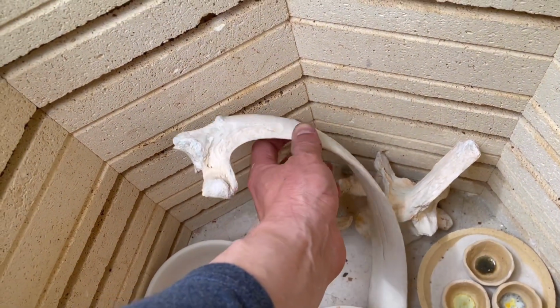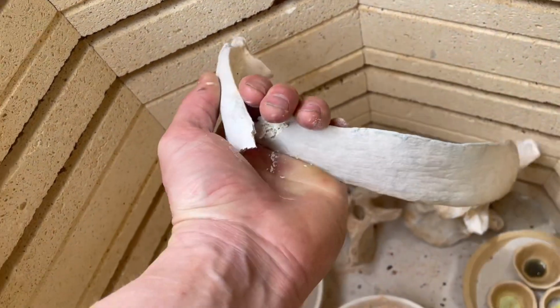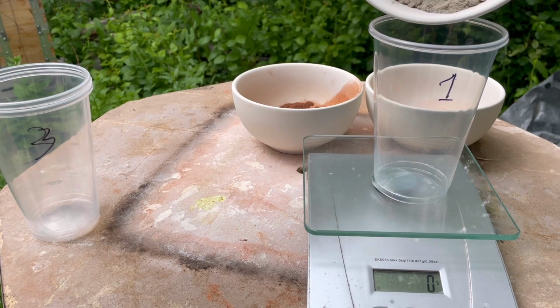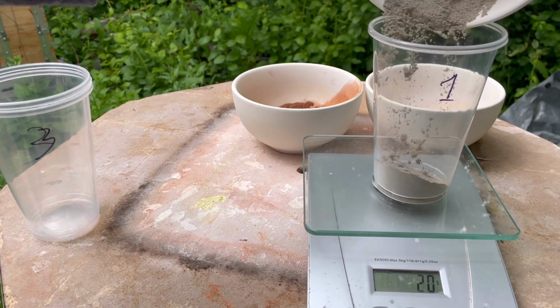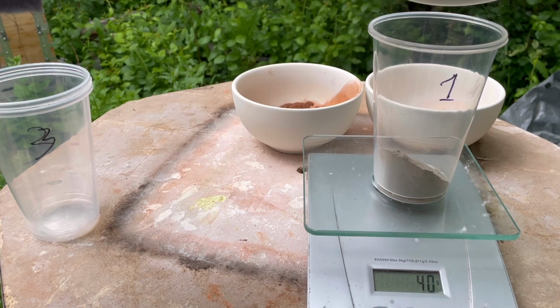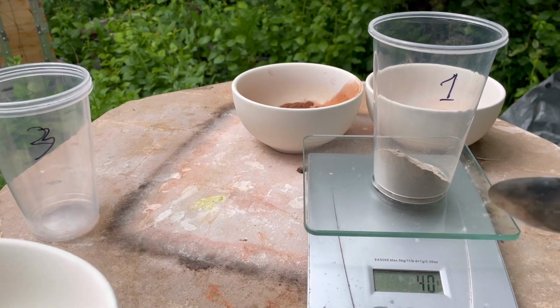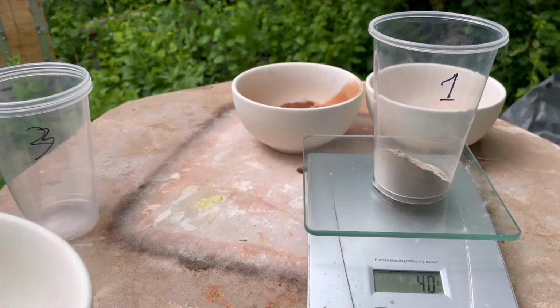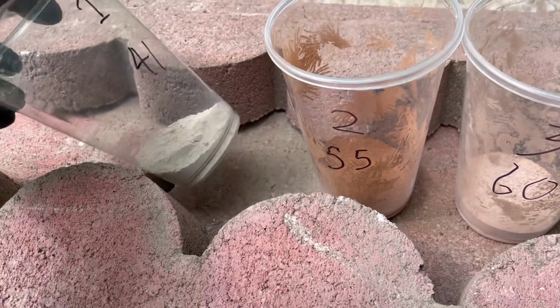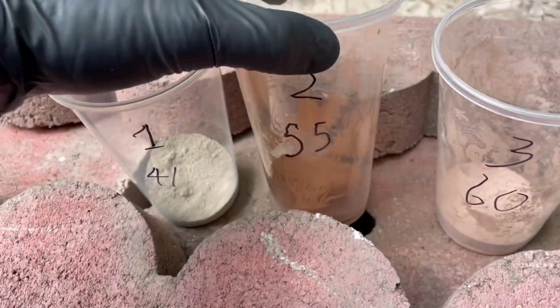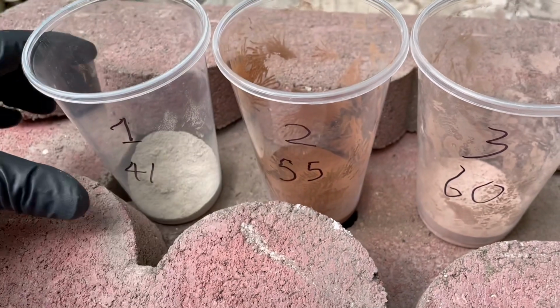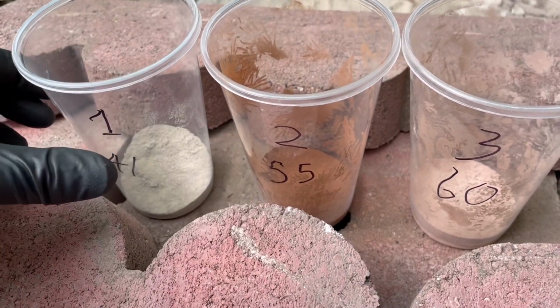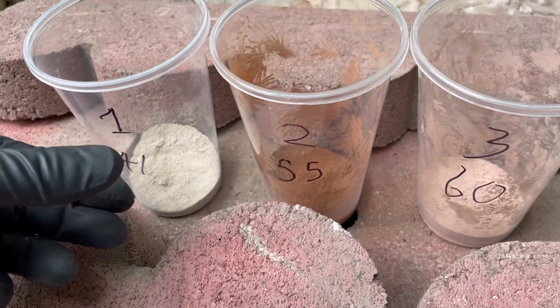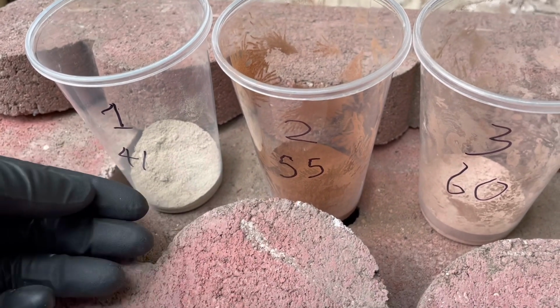The bones look pretty good though. Yep, those will grind up just fine. Remember, we started with 60 grams. Now it's 41. The difference, mostly, is CO2 in the case of this sample. So now that the samples have been roasted to remove volatiles and thoroughly oxidize them, the next step is to combine them with something to make them fuse or melt and become liquidy at temperatures that we can achieve.